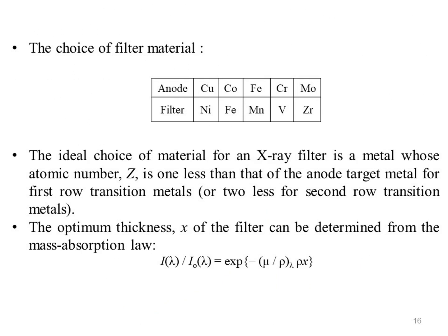Note that the filter also removes much of the high energy background radiation. The choice of filter material depends upon the choice of anode material in the X-ray tube as shown in the following table. This is anode, this is filter. Anode: copper, cobalt, iron, chromium, molybdenum, and filter: nickel, iron, manganese, vanadium, and zirconium.